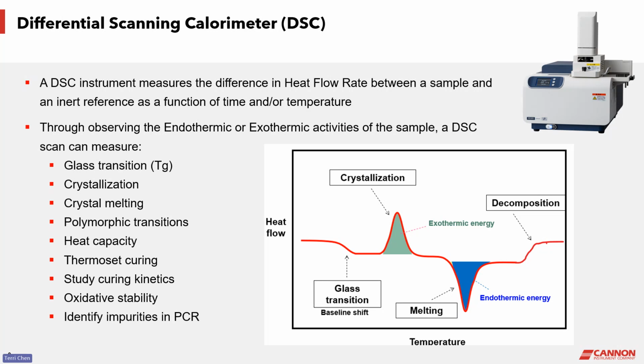DSC is probably one of the most popularly used calorimeters in polymer industries. A DSC instrument measures the differences in heat flow rate between a sample and an inert reference. It can perform the measurements as a function of temperature or time. Through observing the endothermic or exothermic activities of the sample, a DSC scan can measure a polymer sample's glass transition, crystallization, crystal melting, polymorphic transitions, and heat capacity. The DSC technique can also be used to study thermoset curing, measure oxidative stability of a polymer resin, and also help identify impurities in recycled polymer PCRs.